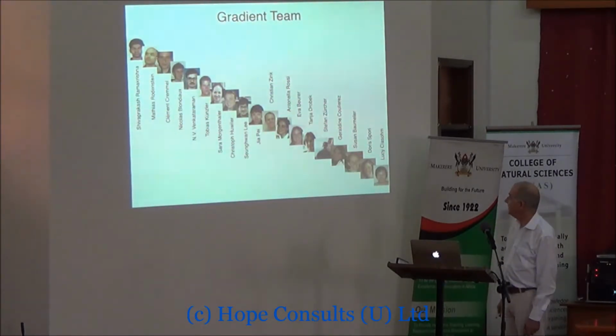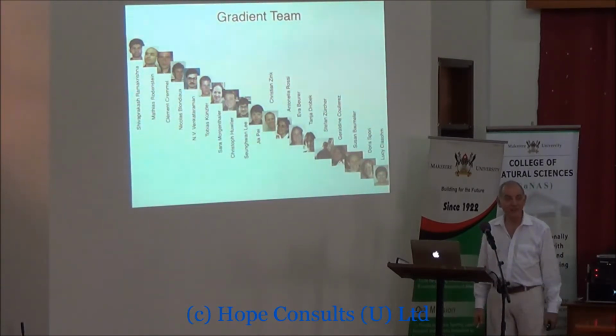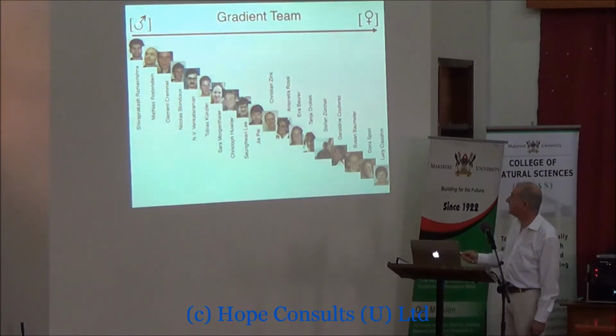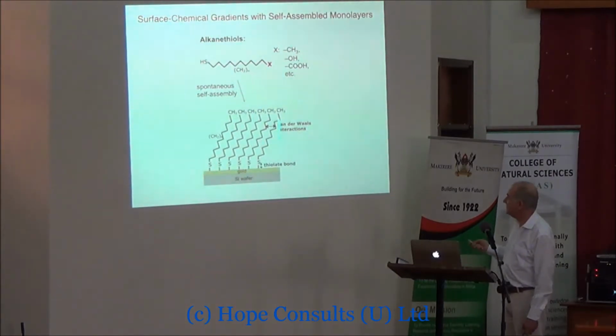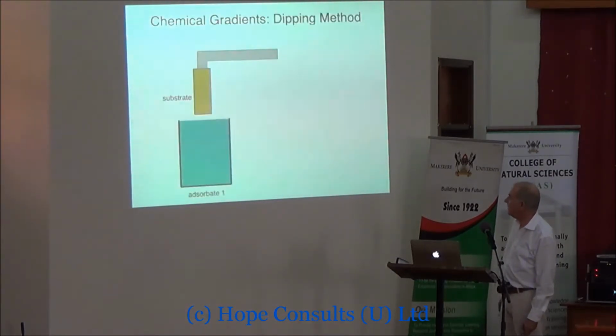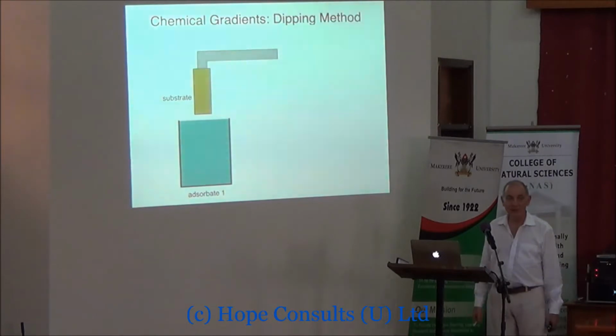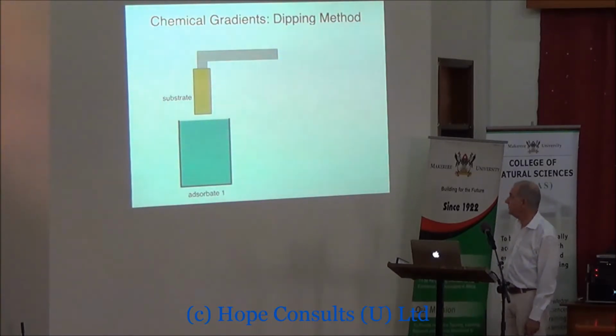and this is the team who's been working on gradients, and as you can see, it's a gradient. It's actually more of a gradient than you might think, because it's a gender gradient as well, more boys at this end and more girls at this end. And we started off using the alkane thiols I mentioned before, and this is one of the things that you can really do anywhere. You just need a clean gold surface, and you do that by evaporating in a vacuum system.